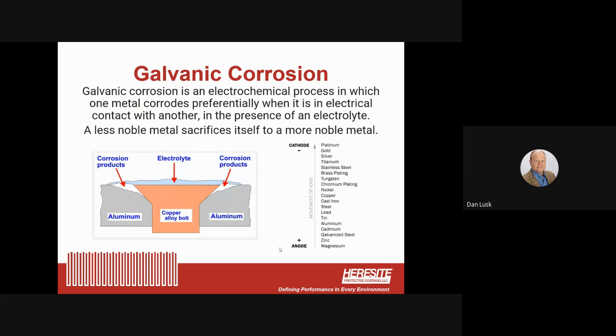There are a few different types of corrosion in particular we deal with. The first is called galvanic corrosion. This is an electrochemical, again, process where metal corrodes when there are two different types of metals together. There are some metals that are nobler or more cathodic than other metals. So those metals will perform better in a galvanic situation. For instance, a nobler metal in what we do is copper. So if there's aluminum and copper touching each other in a corrosion cell, the aluminum will sacrifice itself to the copper and it will corrode or deteriorate. So what we do with a coating is keep that aluminum and copper apart so there's no galvanic corrosion.